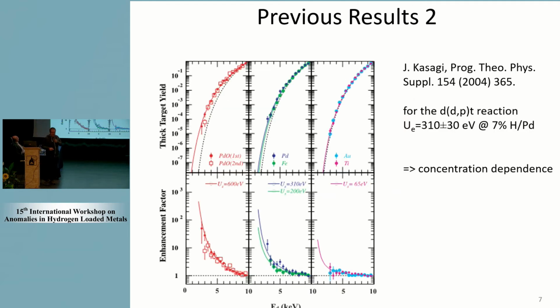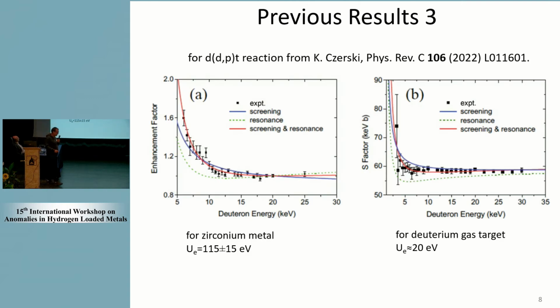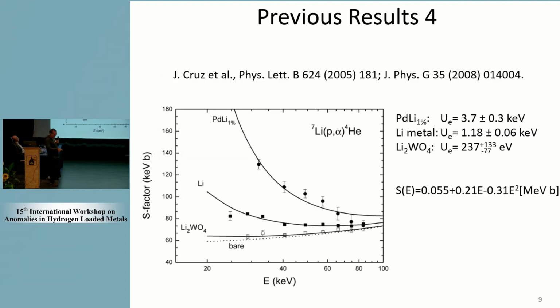At about the same time, Kasagi's group from Japan produced very similar results. The interesting point here was that the highest screening was measured in palladium oxide. They measured like 600 electron volts, and palladium oxide is an insulator, so it seems that this effect, large electron screening, is not limited to metals only. This is an insulator. The other two results were fairly old. This one is fairly new, but Konrad talked about it a lot, so I will not repeat it. Natalia mentioned this one as well.